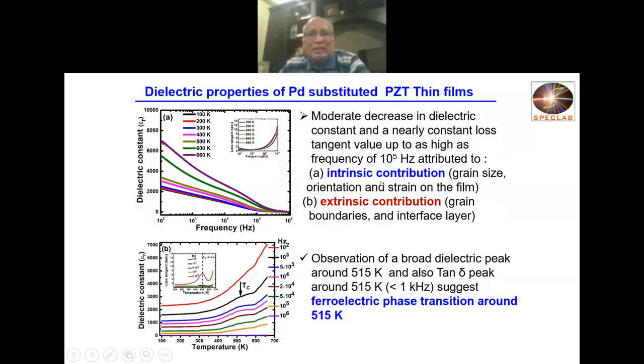Here's the dielectric data. There's a moderate decrease in dielectric constant, and nearly constant loss in this region. This is constant loss, and then suddenly around 10 to the power 5 frequency range, it starts going up. So these losses are basically due to the strain in the film, extrinsic contributions, oxygen vacancies, all kinds of things are there. Interface layers are there. So this material still has to be studied considerably in order to reach any further conclusion on this one.